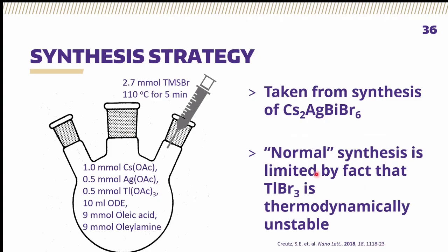We could not employ the traditional Kovalenko method of perovskite nanocrystal synthesis because trivalent thallium bromide is thermodynamically unstable. When it is formed metastably, within a couple of seconds or minutes it easily disproportionates and creates thallium-1 bromide and elemental bromine. So we used instead acetate precursors, including this trivalent thallium. Remember throughout this whole talk, this is a trivalent thallium species. And a ready bromine donor, trimethylsilyl bromide, as the injection material to complete our reaction.